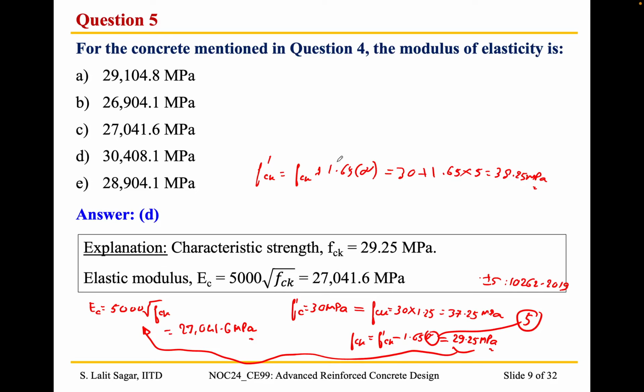Can we conclude that if your cube strengths are more than 38.25, then only you have achieved the characteristic strength of 30 MPa? Yes, that is one aspect. When it comes to concrete there are different parameters, but for strength, if we are able to achieve 38.25, we are adhering to the codal guidelines, and that qualifies as an M30 concrete. But if you are casting multiple cubes and they are falling below this compressive strength, I don't think it will qualify as M30 concrete. It is very important that a significantly high number of cubes tested have this minimum compressive strength.